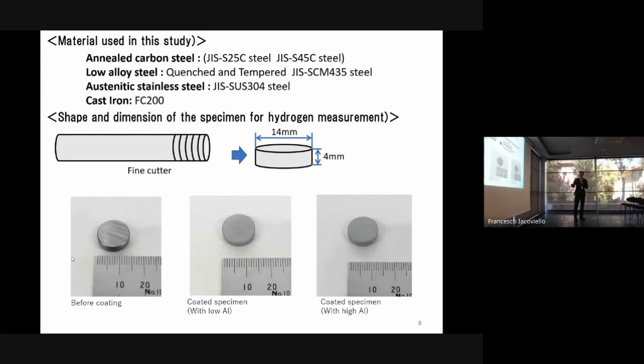Experimental method. These are the materials used in this study: annealed carbon steel S25C, S45C, low alloy steel SCM, austenitic stainless steel SUS 304, and cast iron. The shape and dimension of the specimen for hydrogen measurement are like this. This is before coating, and these are the coated specimens. I prepared two types: low aluminum content and high aluminum content specimens.